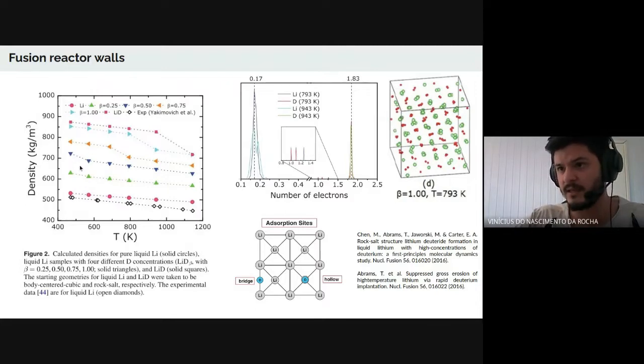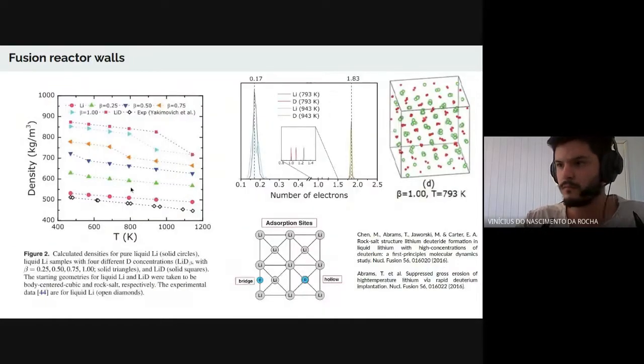Here we can see densities of pure liquid lithium, the solid circles, and liquid lithium samples with 4 different deuterium concentrations. So we can observe that the density grows. These quantum solutions suggest a design principle. High deuterium concentrations in liquid lithium nucleate solid lithium deuteride, which could improve the thermal robustness of the fusion reactor first walls.